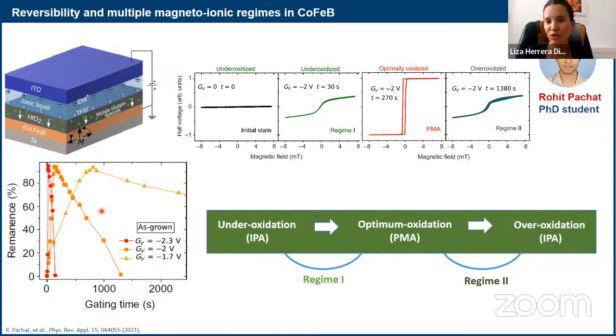This is something important to mention, because related to reversibility we can see a lot of things in the literature where we say, well, with this oxide it is reversible, with this oxide it is not reversible, with this oxide it is not working at all. So up to this point we were saying, well, maybe there is an issue with the type of oxide. And then we tried to do reversibility experiments in this system.